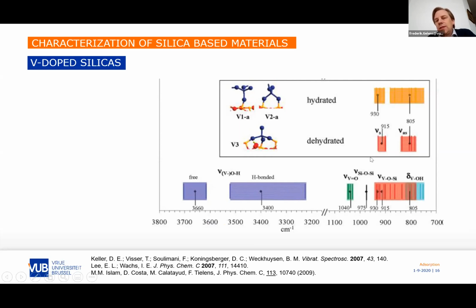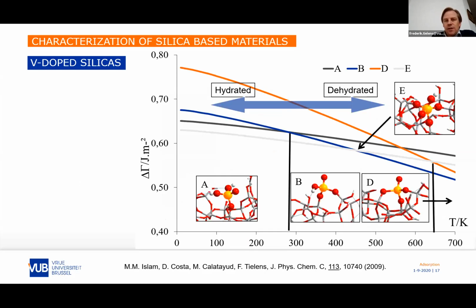So in fact, what we could see is that there is an equilibrium between hydrated and dehydrated states. We see a shift going from these structures to these structures, and vice versa. This is the phase diagram. What is interesting here is that in modeling we can do a very systematic study, and so besides grafting we can also insert. Although this will depend experimentally on the way you synthesize it. So here what we can see is that, for example, a 4 coordinated vanadium might be quite stable before 450K, but depending on the way you synthesize it, you will see it or not.